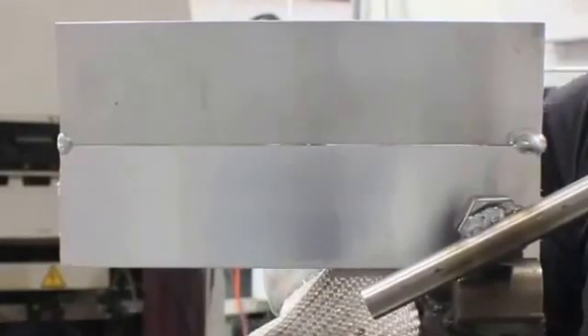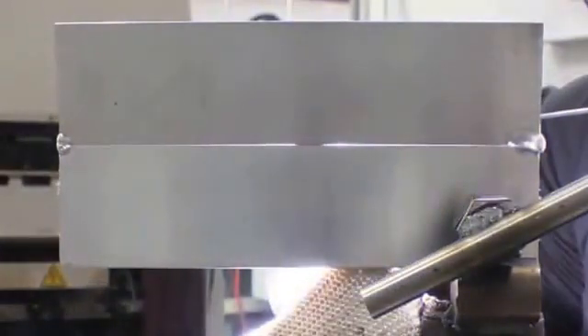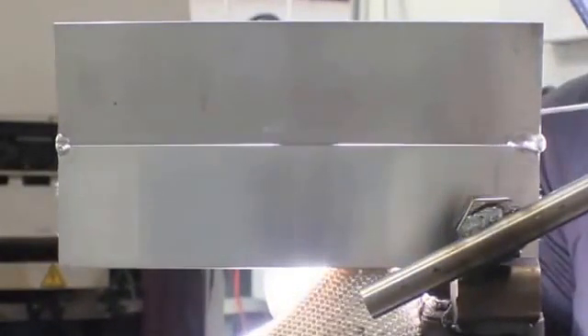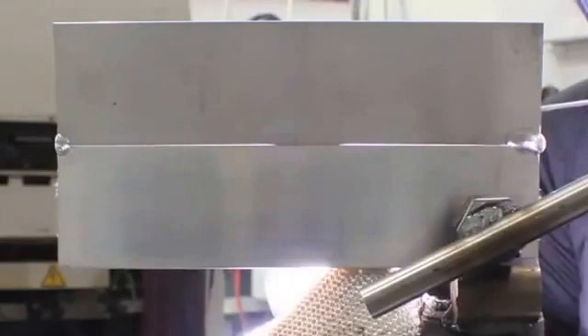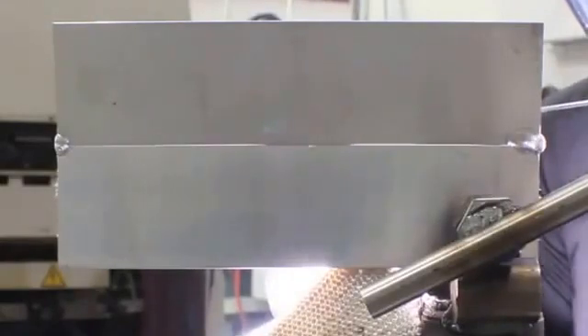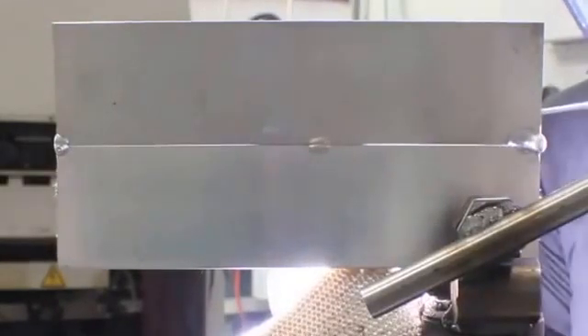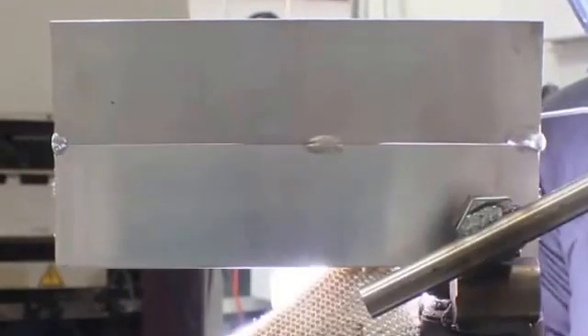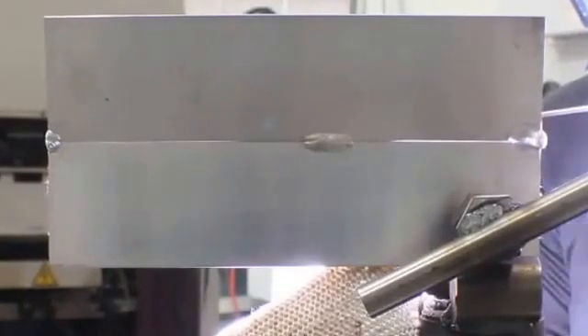And here I'm going to show you something interesting. I'm going to show you the backside. You can watch that puddle kind of form and push through. Now there's oxide film on aluminum, so you watch it barely come through there, but it doesn't melt together yet. Now it finally joins together, but it's like there's a peel coat on there almost. You're not really seeing a puddle on the backside.